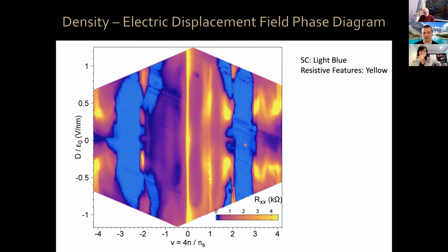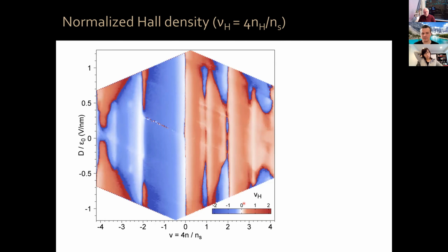And what we decided to measure is the normalized Hall density. So this is the Hall density, which is proportional to 1 over the Hall voltage, multiplied by 4 and divided by the superlattice density, so that we can normalize this and call it the normalized Hall density, analogous to the filling factor that I told you earlier. This is now the normalized number of free carriers per unit cell in your system, so to speak. Now if we measure this normalized Hall density as a function of again filling factor and transverse displacement field, you can see again that it's a complex phase diagram.